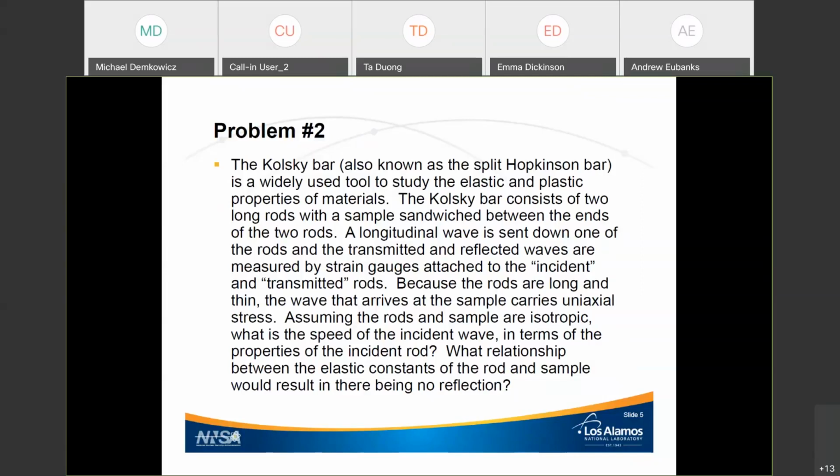Because, well, the accelerations lateral to the axis are, kind of hard to discuss conveniently, due to, if you will, induced stresses. The initial stress that is applied to the bar is strictly sigma 1,1. But there are off-diagonal components in the elastic constant matrix that allow that to relate to the strain in the lateral direction.